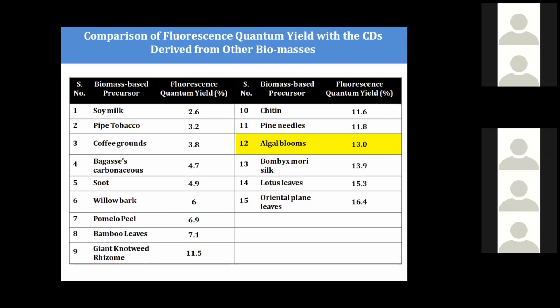So we have compared the quantum efficiency. Here the benchmark of the photophysical characteristics - one always looks for the highest quantum efficiency carbon dot. That's the target we always look at. Now we could really see that compared to literature-known materials from natural resources, algal blooms were found to be around 13%, almost at the upper edge. It is not the highest, but still in the upper edge of the quantum efficiency that one finds.